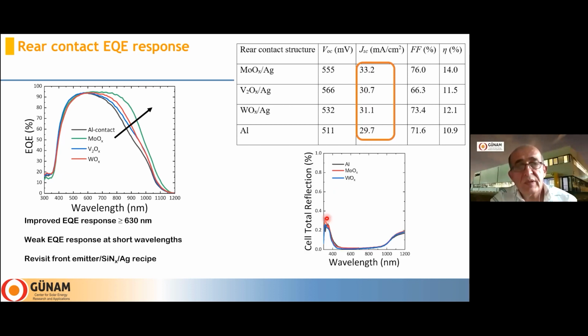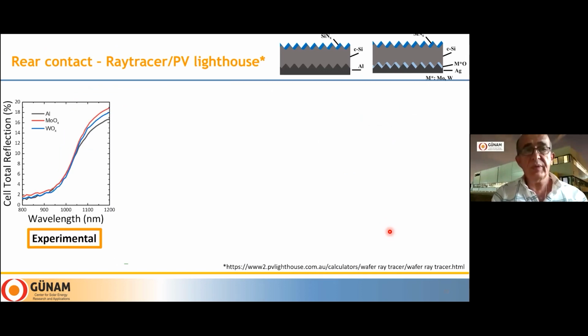with the reflection measurements. So we don't see the details here, but the reflection with the molybdenum oxide is highest. This is showing that we have a very small amount of parasitic absorption on the backside. Here is showing the experimental total cell reflection. So here we obtain the highest value from the molybdenum oxide, which is showing that we are losing some due to the reflection. However, it is also showing that there is very little absorption in the molybdenum oxide layer, which is also good.